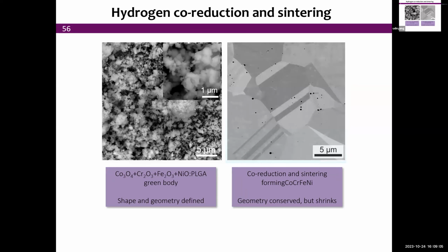And you say, well, okay, so what's the big deal? The really interesting thing is that chromium oxide, if you look at its stability, should not be reduced with hydrogen. It is more stable. It's sufficiently stable that pure hydrogen will not reduce chromium oxide. So what we achieve here is a reduction of chromium oxide in the presence of already reduced cobalt, iron, and nickel. I'll explain in a second why this is happening, but let's look at it. We start with those extremely fine powders or powder agglomerates where we have all 4 elements.